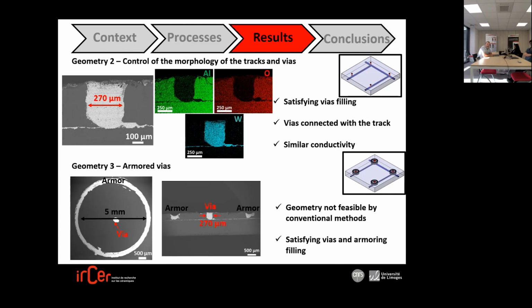Another geometry is armored vias. As you can see on the picture at the bottom of the slide, we have printed at the center a via, which is connected to horizontal tracks. And then we have made a cylinder of metal of about 5 mm diameter in order to armor the via. Here we can see that this type of geometry has been made with the use of additive manufacturing technologies, and this geometry is not feasible by conventional methods. The armored via has been well filled and is okay for us on its shape.